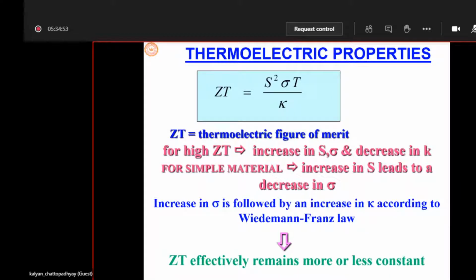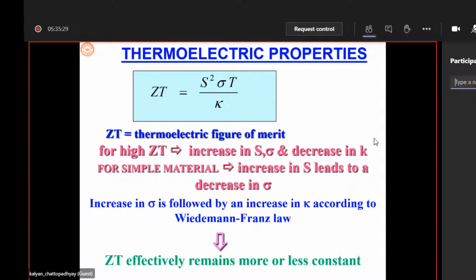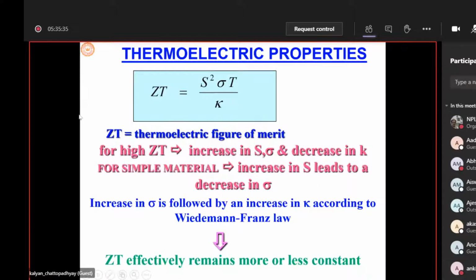Why? Because if you look at the thermoelectric figure of merit, it is well known that to achieve higher ZT, that is the figure of merit, you should increase sigma, that is electrical conductivity. At the same time, you should decrease the thermal conductivity. But you know that they are not independent. They are basically dependent. If you increase sigma, essentially it will lead to an increase of K by the Wiedemann-Franz law, and ZT remains constant. So there was a proposition by Hicks, who suggested that if you can find some system where you have independent control of sigma and K, then it is possible to obtain higher ZT.